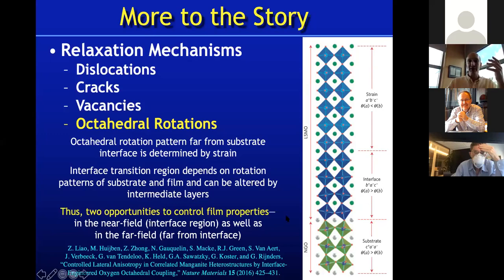where you're damping this. It has the opportunity to change the properties, and indeed these authors found changes in the magnetic properties. A huge boost came about in the Curie temperature of the lanthanum strontium manganite by changing the octahedral rotation pattern. Other groups have found the same in strontium ruthenate. It was very close in time. Both groups independently found that they could have these intermediate layers between magnetic layers. So in this case, it's lanthanum strontium manganite, and in the case of the group from Kyoto University, it was the strontium ruthenate. But again, changing the magnetic properties came about from this intermediate layer. So there are more opportunities, I would say, than the simple cartoon that I showed you at the beginning would lead you to believe that can come from strain engineering.